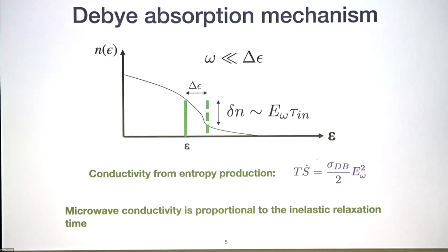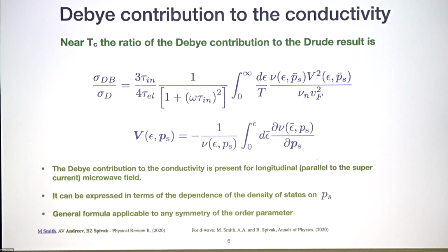Okay, so let me start with the simplest. That's an illustration of Debye relaxation, how this actually occurs, because quasi-particle levels move in time in energy space, setting off inelastic relaxation processes. Boris already explained that, so let me skip it. I'm going to borrow on the results that Boris discussed, where we studied the Debye relaxation in uniform systems, where it can be expressed in terms of the dependence of the density of quasi-particle states on the superfluid momentum, and apply these results to this non-uniform system. I just want to mention that we have microscopic results for both S-wave superconductors and D-wave superconductors for uniform systems. I'm going to borrow on the results for S-wave, for the dependence of the density of states on P_S.